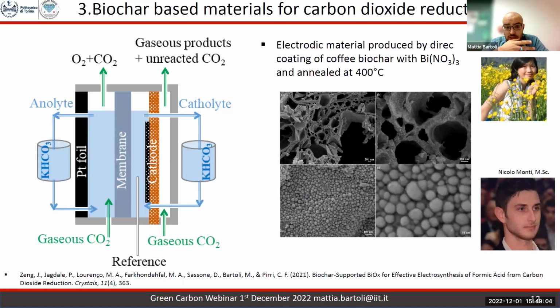The setup that you saw here is the common flow cell setup, where a flux of gaseous CO2 is inserted, absorbed in a basic solution, and two electrodes, a cathode and a platinum foil that acts as anode, are divided by a membrane. The point is, the electrodes that are working, the cathodes, are based on carbon paper, carbon black, and so on, so we try to fully replace them with biochar.